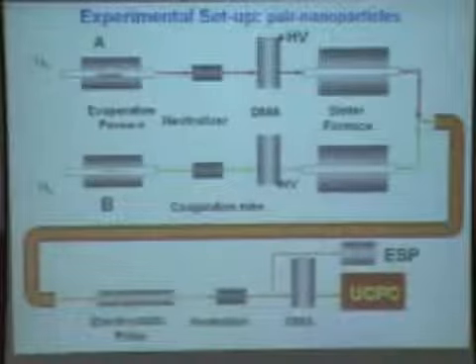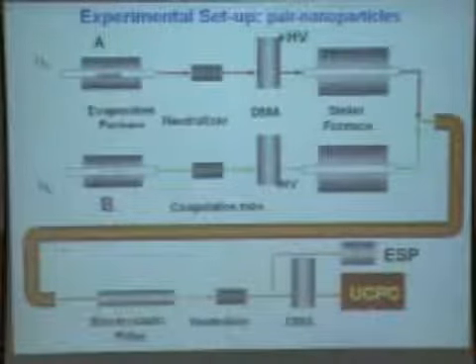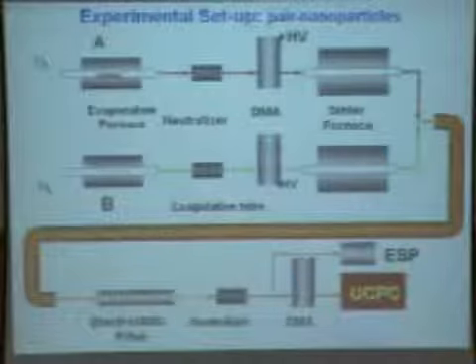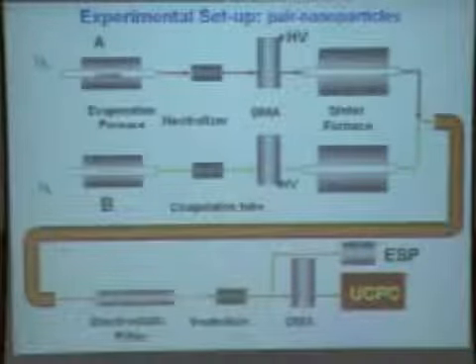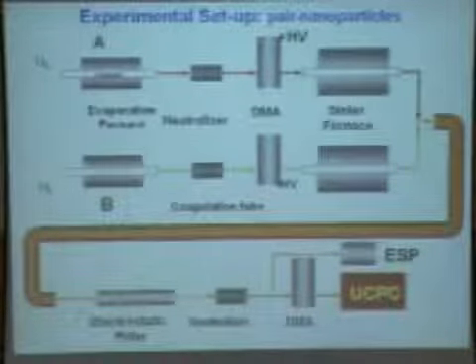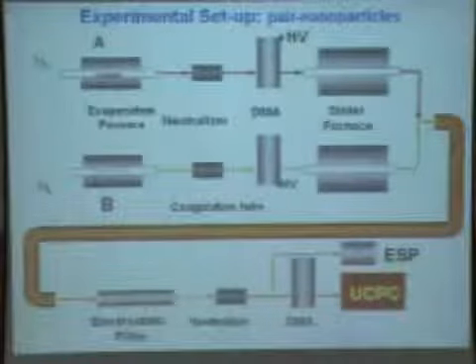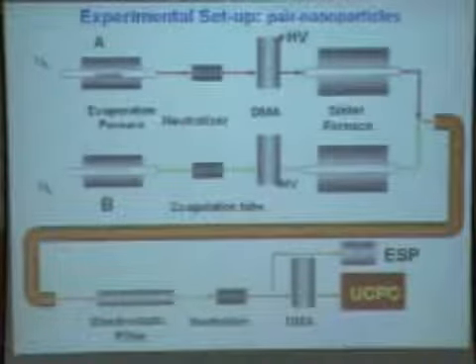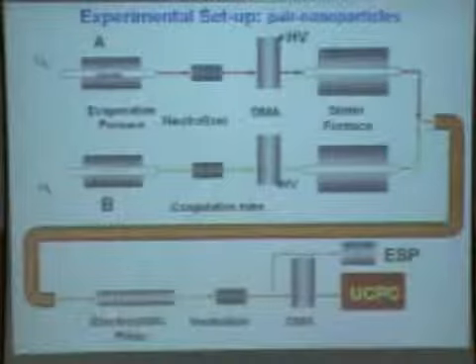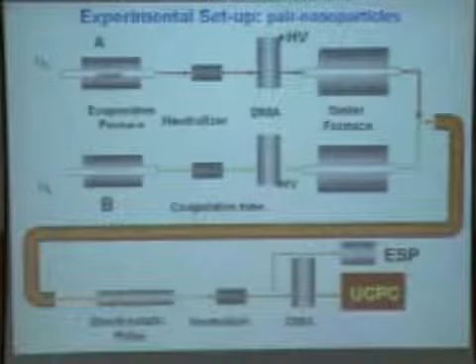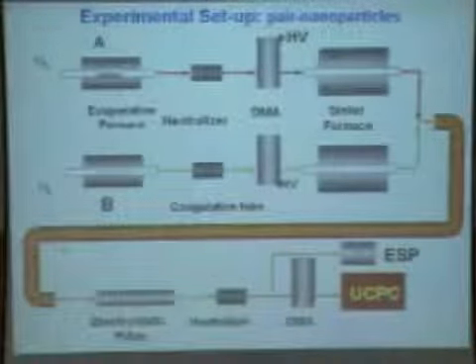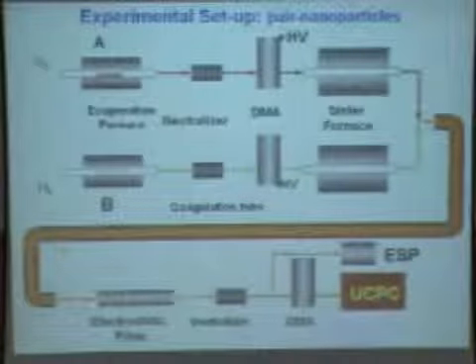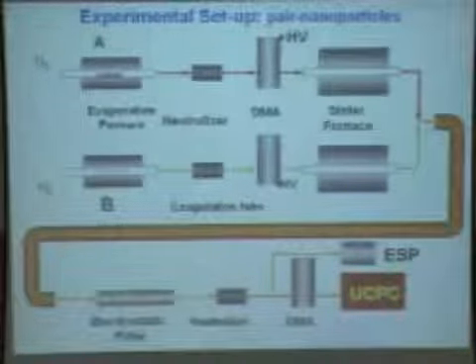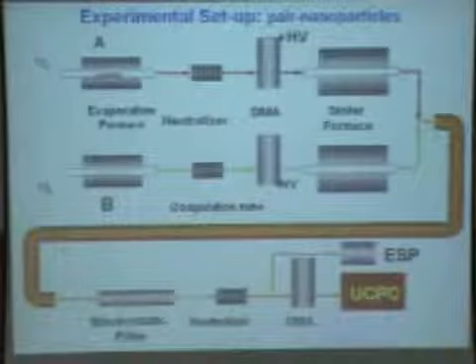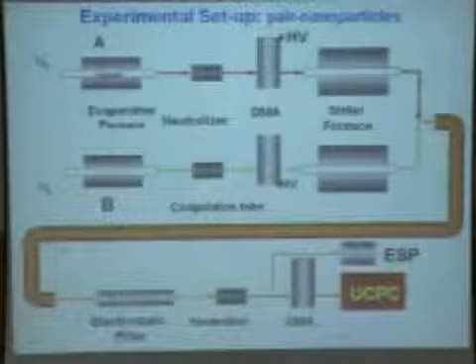These positively charged and negatively charged A and B particles are flown through this coagulation furnace where they collide with each other. So positively charged particles and negatively charged particles come together, and then we filter them because some of them have not collided, and they will have a charge. Those charged particles are removed. The only particles which are allowed to go in this direction are the neutral particles. That means the particles which are neutral must be the particles which are in pairs.